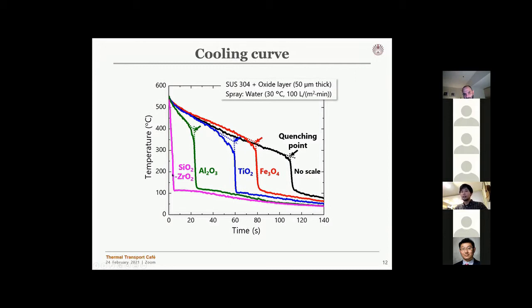The peculiar case is when we had a silicon dioxide layer—we didn't see the film boiling region at all. Once we started the spray cooling experiment, the temperature dropped rapidly to around 100 degrees Celsius, so we couldn't define a quenching point in this case. We also found inconsistent quenching points depending on the composition of oxide layers.